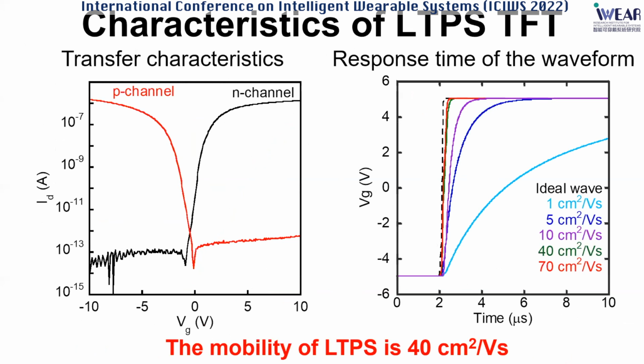And thanks to the high speed of low temperature polysilicon, which achieved a mobility over 40 square centimeters per volt second, here is the waveform of the time response. And this is the simulation. Once the mobility exceeds 40, that exhibits sufficient response time. And our low temperature polysilicon can meet this requirement.